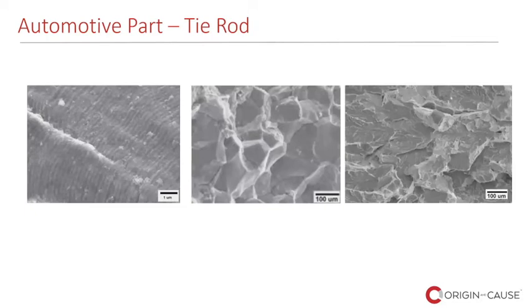So as I mentioned earlier, the tie rod failed as intended. If the tie rod had been defective, it would have failed in a different mode, and there would be significant signs on the fracture surface to indicate that. On the left image, you see those consecutive markings, which are called beach marks, and they are evidence of a progressive failure, an indication that the tie rod would have failed as a result of fatigue.